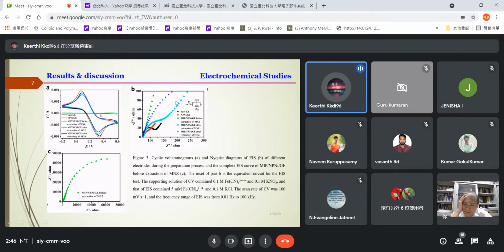It is shown in the green color response. The decrease in the response is due to the non-conductive nature of the polymer. Moreover, the polymer film fully covered the electrode surface, so there was no channel for the active probe except the electrode surface. After removing the template, the drug metronidazole, from the polymer network, some channels were created, so probe ions could pass through the cavities and reach the electrode surface. This response is shown in sky blue. Then the rebinding of the metronidazole was performed, and its response is shown in blue.